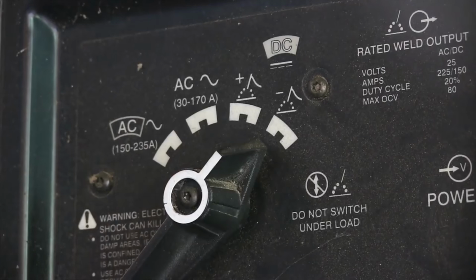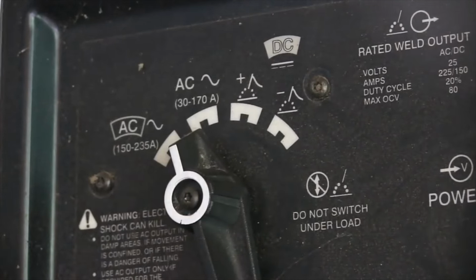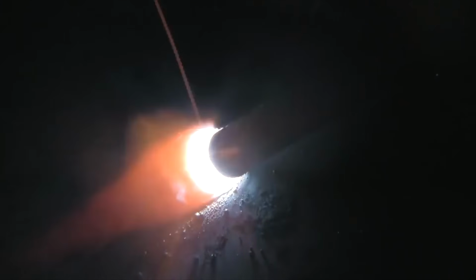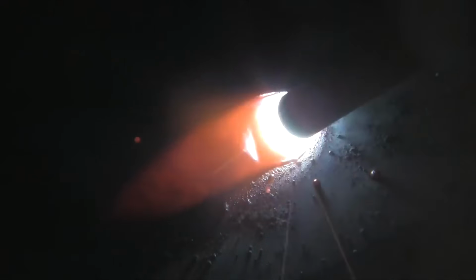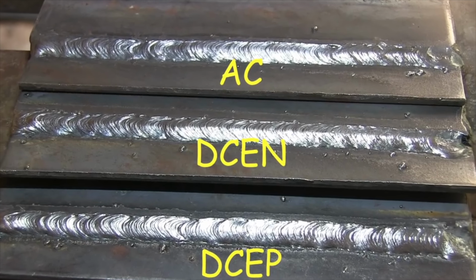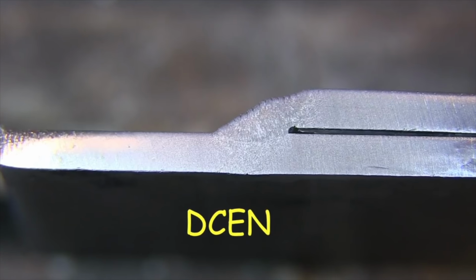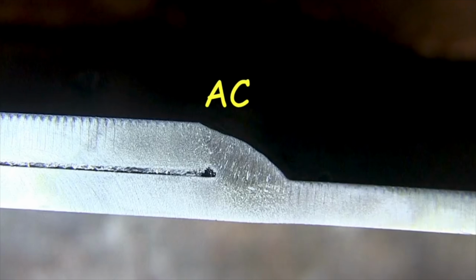So will a 6013. An awful lot of 6013s are used on AC buzz boxes. In fact, I did a video a while back. I compared DCEN to DCEP to AC. Three different welds, cut and etched all of them. The puddle actually looked almost identical on all three welds. Very subtle differences, no matter if I was on DCEN, DCEP, or alternating current, maybe a little bit more spatter on alternating current. But cut and etch test and the visual all looked very similar. Not much difference at all. Big difference when you get out of position for the different polarities.